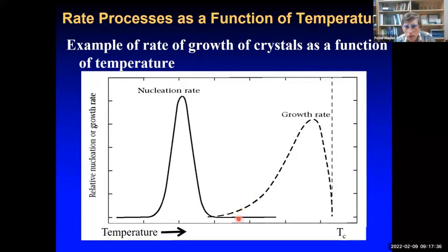So is the rate going to increase with temperature or decrease with temperature? If we start from low temperature, we find in this case that the growth rate is increasing up until this critical temperature. And then after that, it actually starts to go down again. So we need to be sure about which side of this growth rate hump, if you like, or maximum we're sitting in our process. The same thing applies to nucleation, which doesn't usually have its peak nucleation rate at the same temperature as the growth rate.